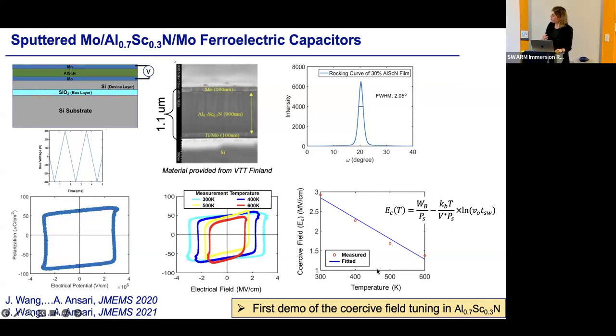Generally, the coercive fields in nitride ferroelectrics are very high, so you need to apply a lot of voltage in order to switch the polarity. So this was the first demonstration of the temperature dependence of these coercive fields in the ferroelectric metal capacitors.